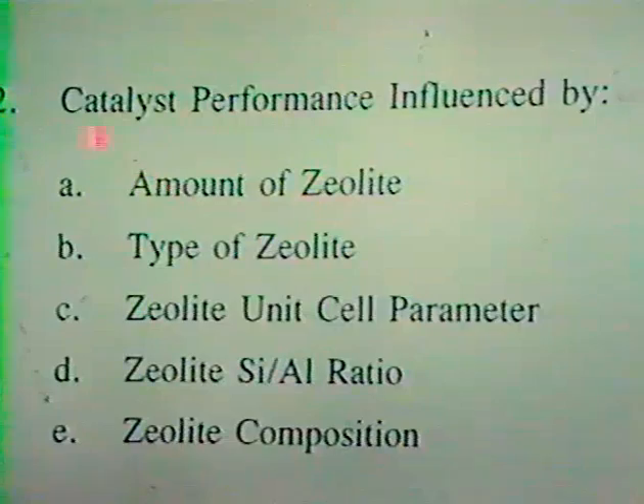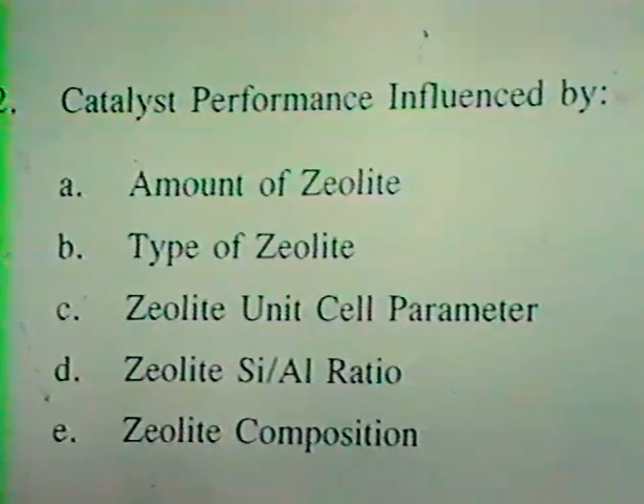The cracking component of the zeolite is influenced by the amount of zeolite and the type of zeolite. The unit cell parameter is an important parameter. Zeolite silica alumina ratio is important. And I didn't go into it for lack of time. The ratio of the zeolite to amorphous components in the catalyst, and particularly whether the amorphous component is alumina or silica alumina or pillared clay or sepiolite or any of several other materials.